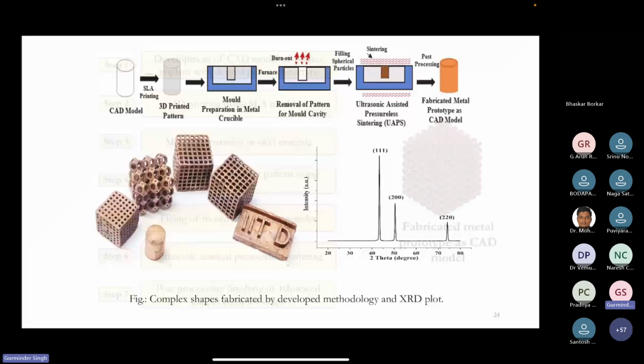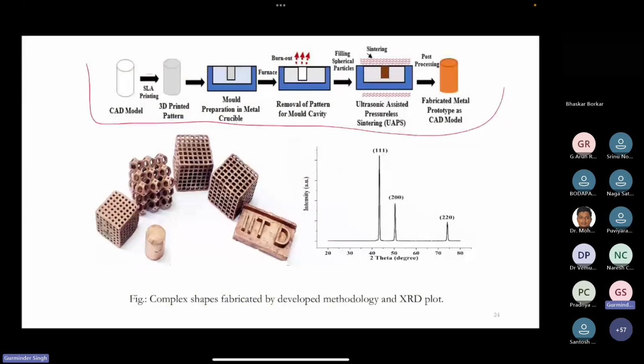So this is the summary of the whole process, starting from the CAD model, making a pattern using polymer 3D printing, SLA in our case, and making a mold using investment casting powder, then making a cavity by burning out the polymer, filling this cavity with powder, and doing pressureless sintering and ultrasonic vibration sintering to make the final product.